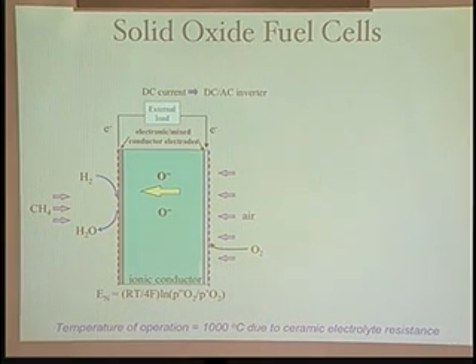But these thick film devices, the thickness of this plate was typically 200 microns. And because of the resistance of that plate, the temperature of operation was limited to 1,000 centigrade. And that's pretty high temperature. And at 1,000 C, if anything can happen at the interfaces, it will happen. So you have to really engineer these electrolyte interfaces well. Otherwise, you get degradation. And 1,000 C also means you can't use metals. Very difficult to use metals. But you'd like to use metals because metals are much easier to form and machine.